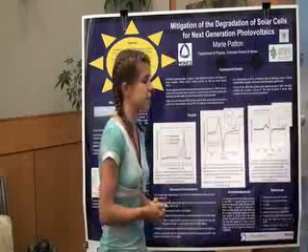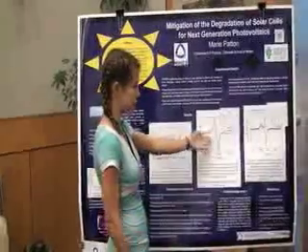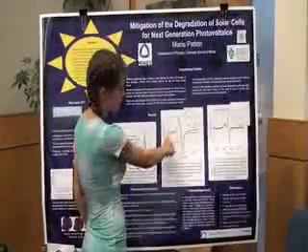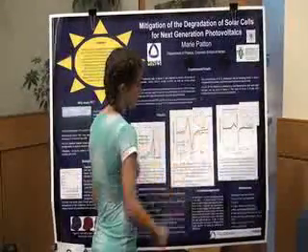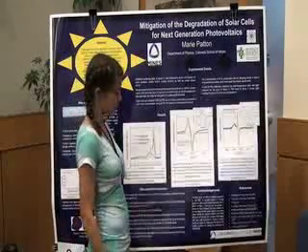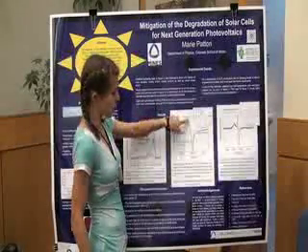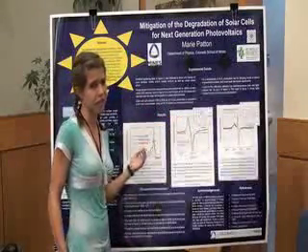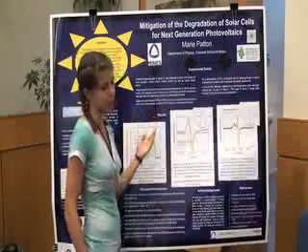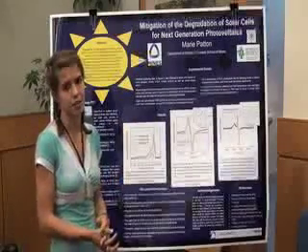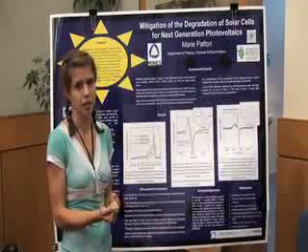What I was looking at is the differences in room temperature ESR, which is this graph here. The red line is the amorphous, and the black one is the 90% crystalline. What's really interesting about this graph is that I've never really seen anything like this shape before in any literature that I've looked at. This little lip here can't really be fit to either a Gaussian or a Lorentzian derivative. So that's interesting because you can't calculate spin densities of it.